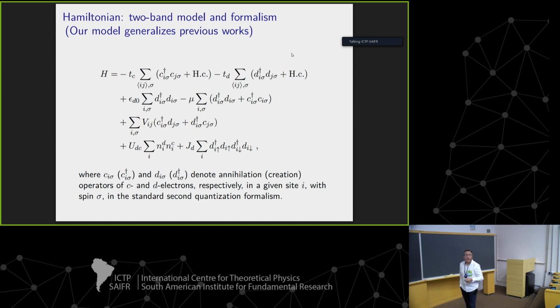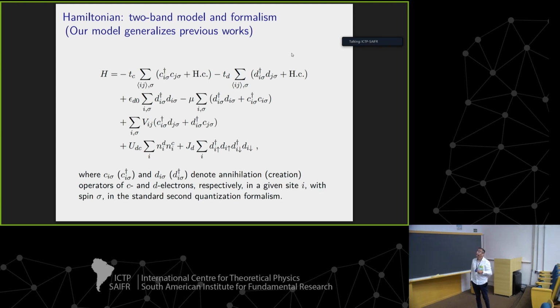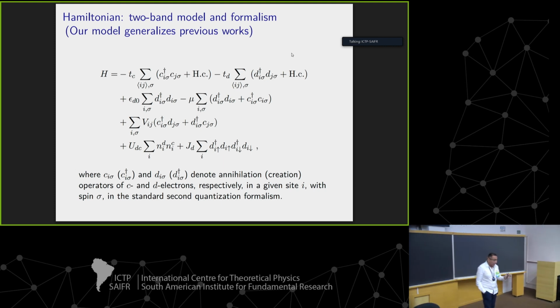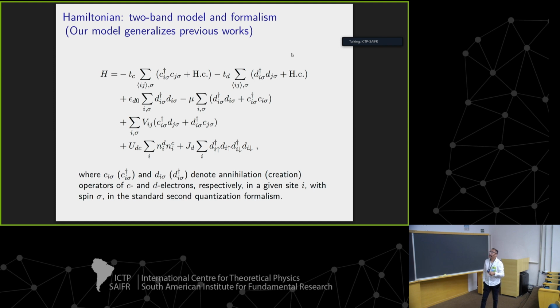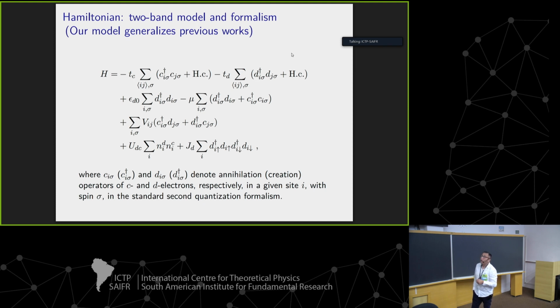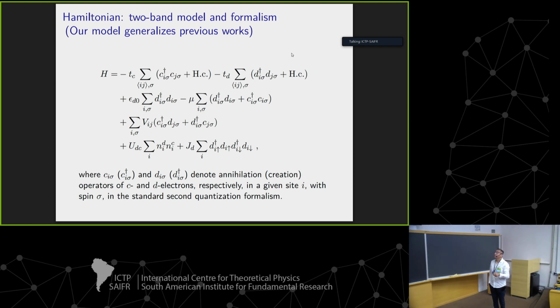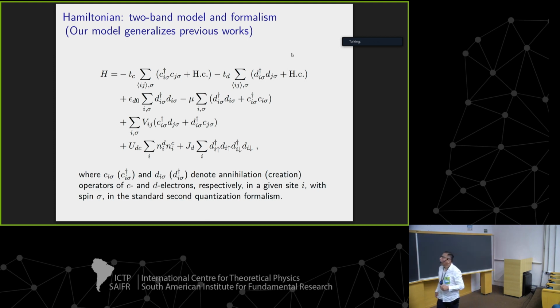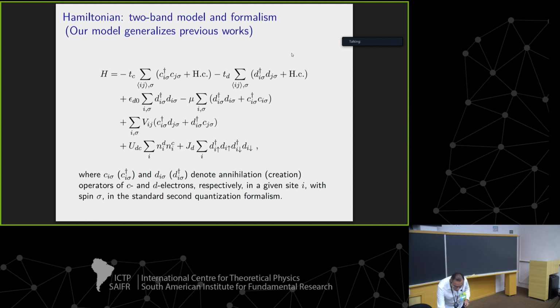So we have a two-band model, still in a square lattice. This term here is a large band. This is a narrower band. This is the relative energy shift between the bands, which can resemble, for instance, the chemical substitution used by experimentalists. This is the chemical potential in standard form. This is the on-site hybridization, which for us resembles pressure. This charge density order comes from this term here, the on-site Coulomb repulsion, as in the previous work. And superconductivity comes in the standard form from this term here. All right, so this is our model. Remember, it's in 2 dimensions.